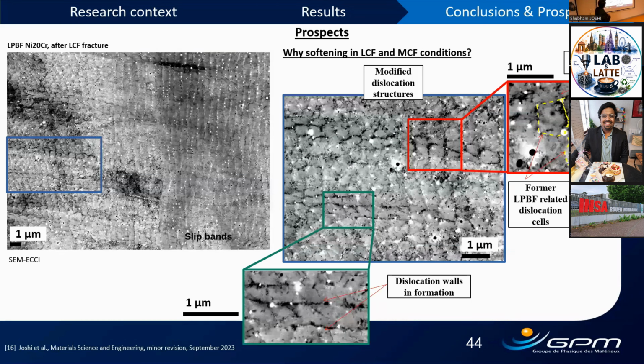So what I said is this is a sample after LCF fracture, first of all, for the LPBF Ni20Cr, and we see a lot of slip bands. And if we magnify one slip band, what we see here is almost like the dislocation wall is getting thicker, and this is not what we saw in the initial state, and the dislocations here seem to be disappearing. I'll just close it.